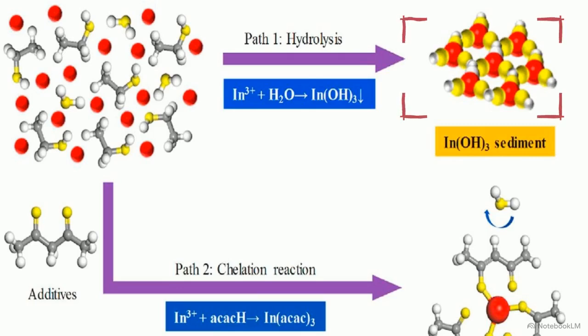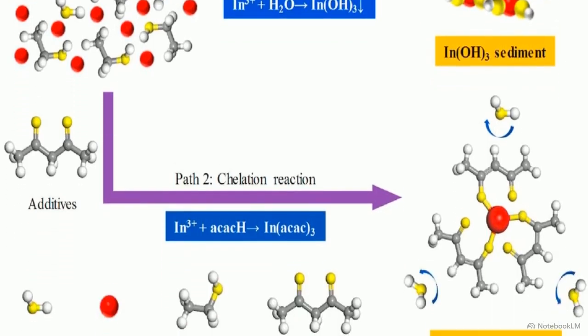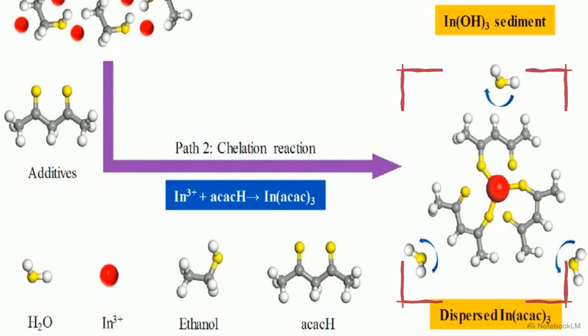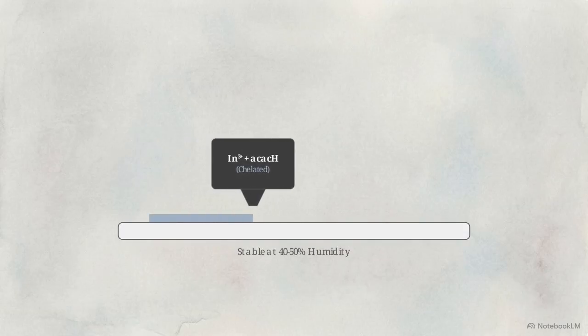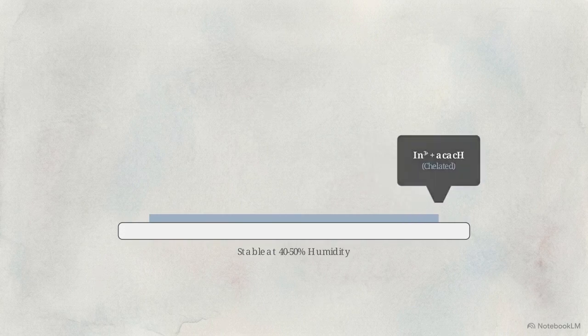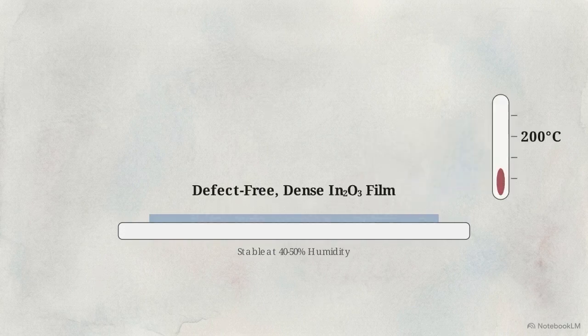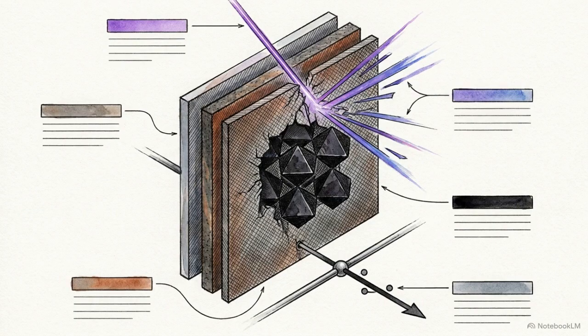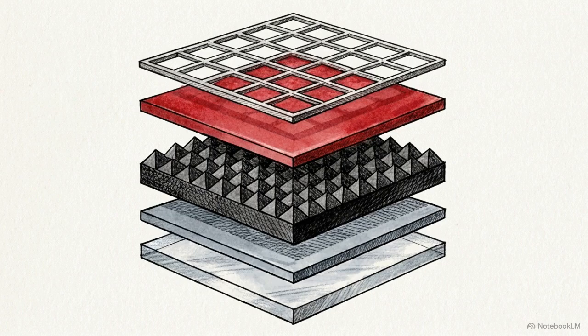Standard hydrolysis, seen at the top, leaves behind an unstable, uneven sediment. But by utilizing a chelation reaction, adding specific stabilizing additives to the precursor solution, engineers tightly control the atomic bonding. Preventing uncontrolled hydrolysis specifically eliminates the microscopic pinholes and cracks, yielding a dense, highly crystalline thin film that can be laid down at low temperatures. Engineering the ETL is an exercise in damage control, extracting the electrons safely while shielding the perovskite from both UV degradation and structural traps.